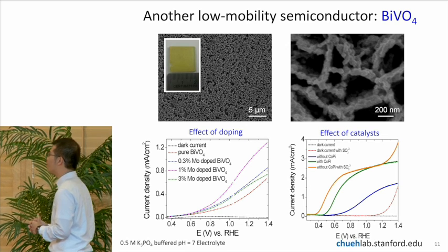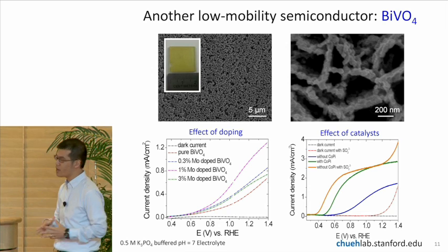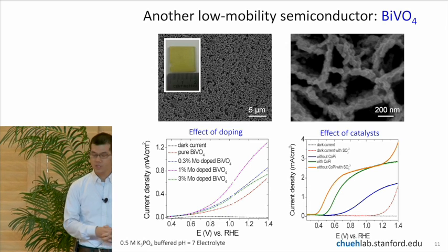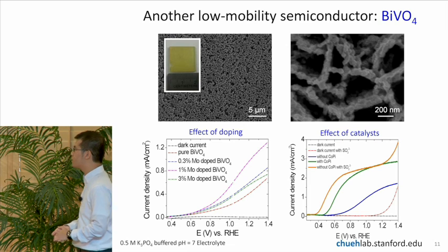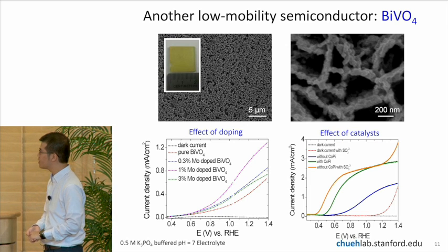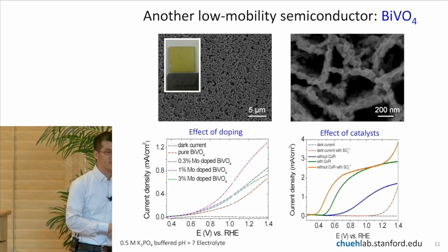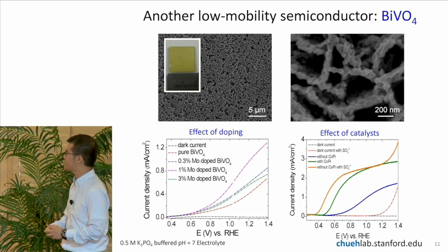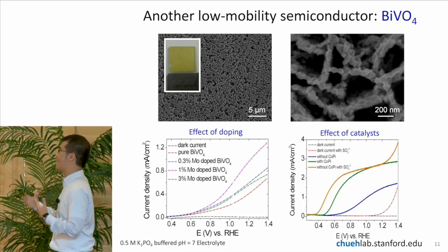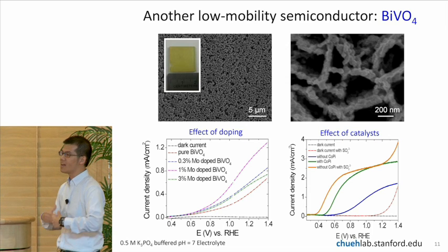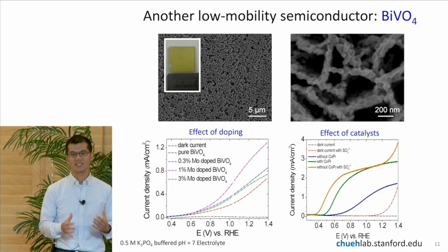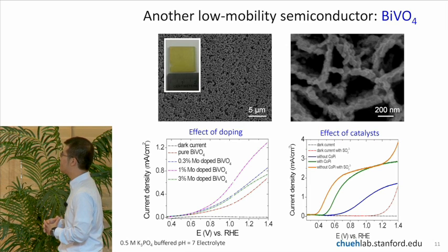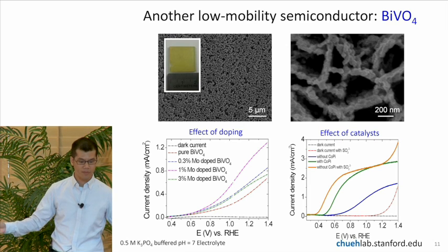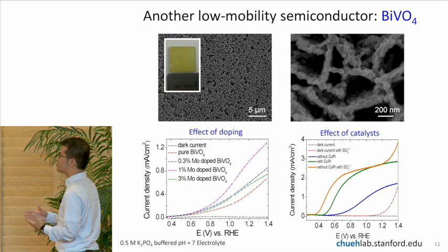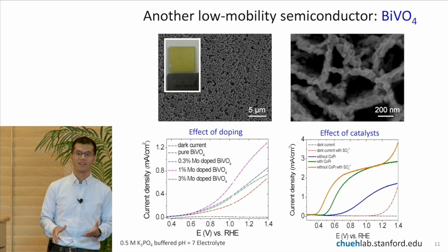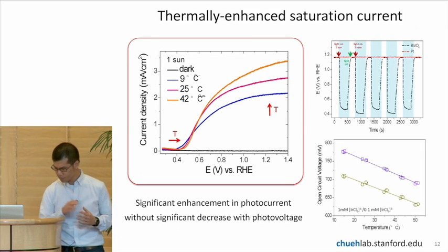So I just show you here some scanning electron micrographs. These are the nanostructures we have created through a series of electrodeposition and pyrolysis reactions. We tried doping the system to improve the conductivity of the majority carrier. We also added catalyst to it. But without showing you too many details, essentially we're able to create state-of-the-art bismuth vanadate material for photoelectrochemical cell at room temperature. So the next thing we wanted to do was to see how thermal energy could improve the performance of the material.